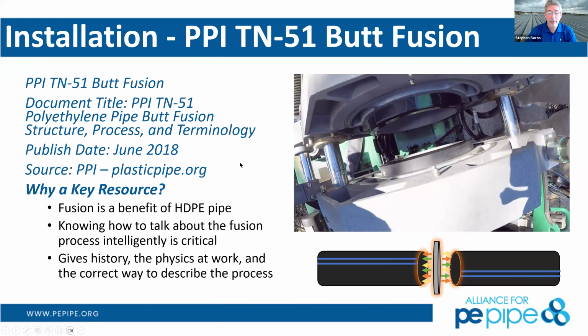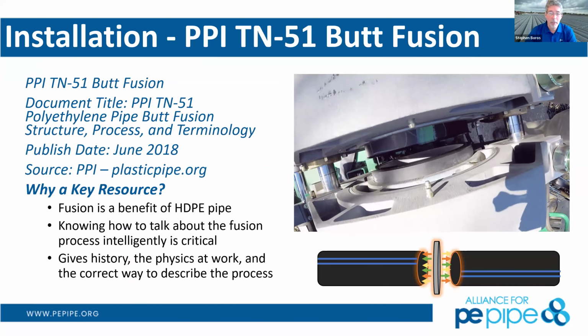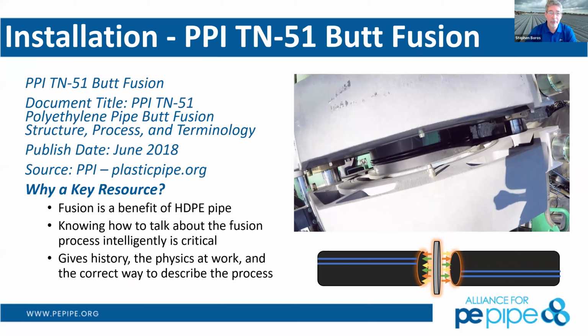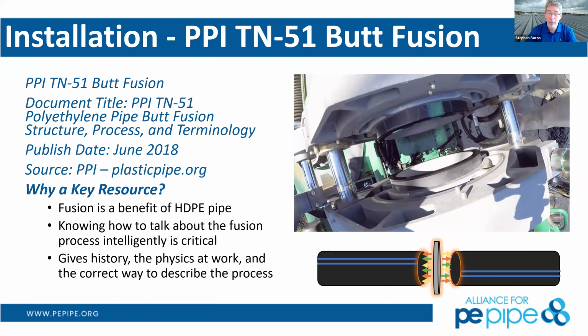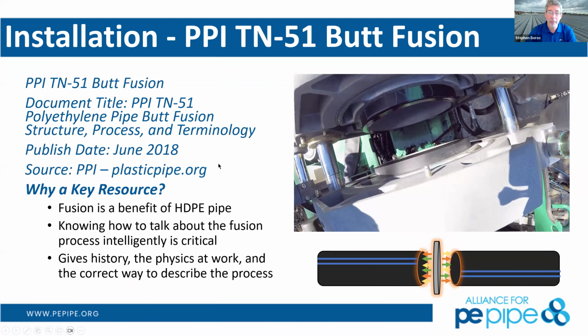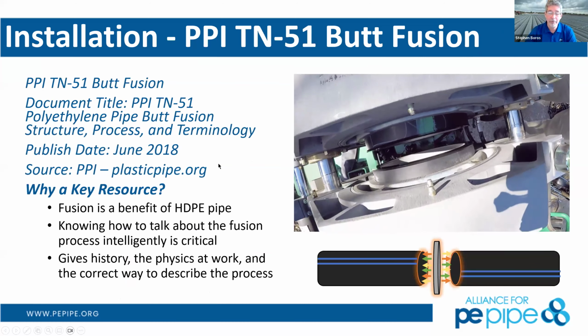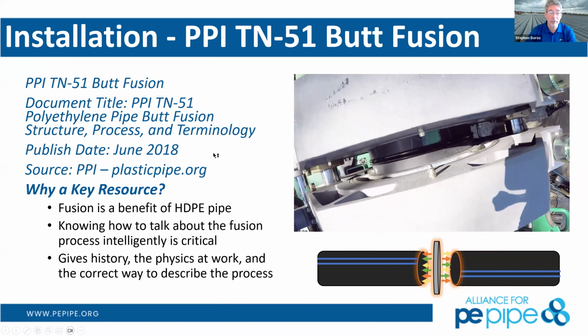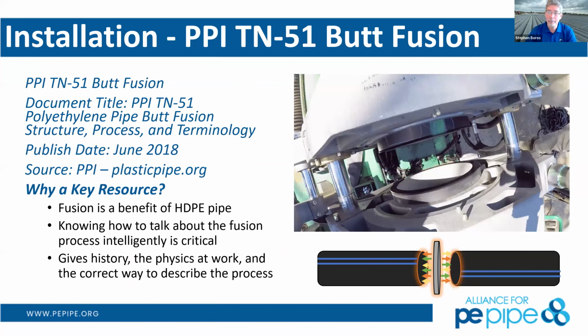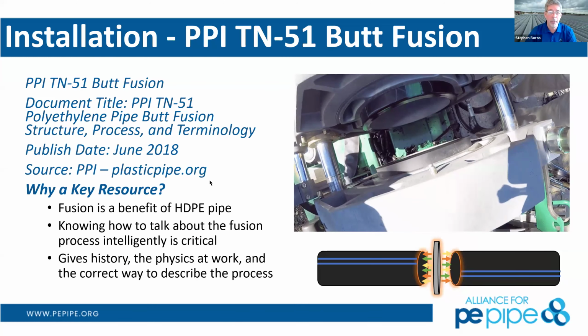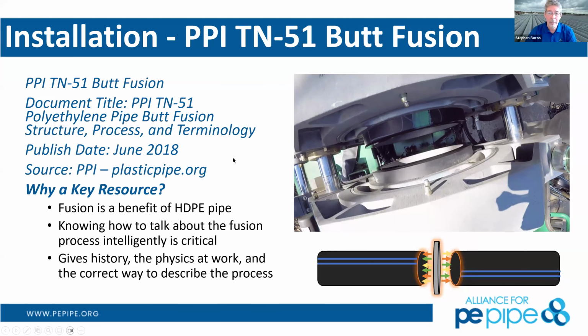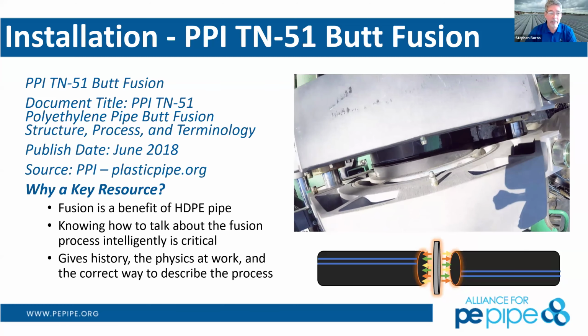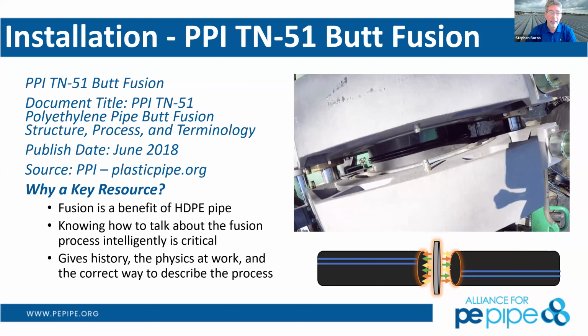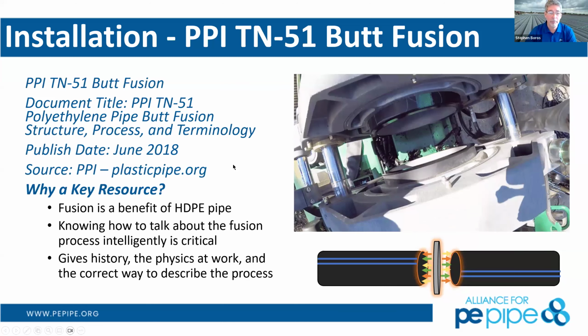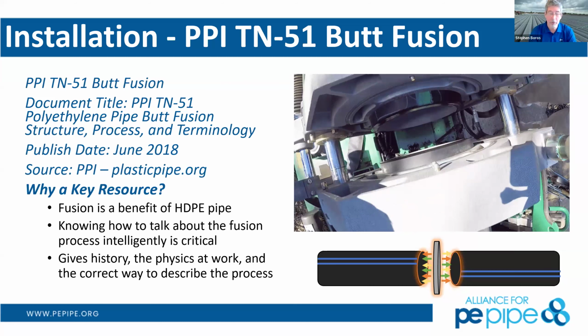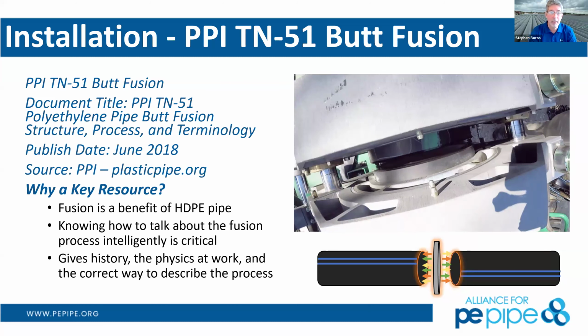TN51 talks about butt fusion. Butt fusion is the number one heat fusion joining method for polyethylene. It doesn't require a fitting. It requires a fusion machine to align the pipe and bring it together in the right fashion. But once it's brought together and fused in this manner, it becomes a monolithic pipe piece at that point. There's no longer a joint that's going to come apart. Again, that joint is now as strong as a pipe. It's fully restrained, and it won't ever be a weak link that's going to be a problem within your piping system. So that's the number one way of doing it.